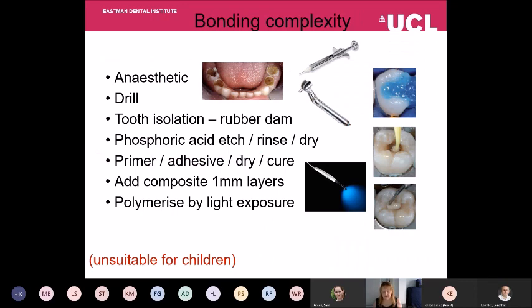It's the bonding complexity that makes the composite really far from ideal for treatment of very young children. You need to have an anaesthetic, a drill, tooth isolation and a rubber dam in order to be able to place the phosphoric acid etchant. Then you have to rinse and dry. Following that, you add multiple steps of primer, adhesive application, drying, curing. And then you have to place the composite in thin, usually 1 millimeter thick layers, and cure each layer in turn by exposure to a blue light.